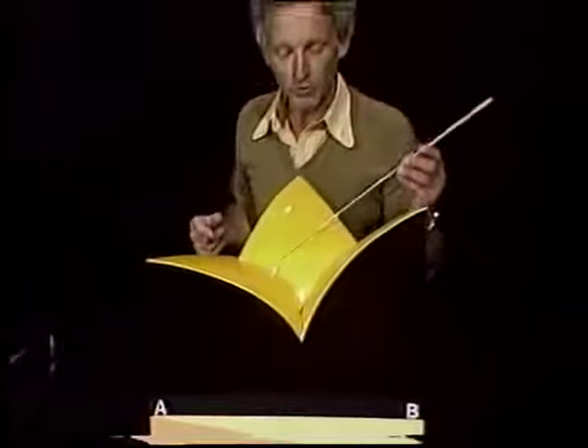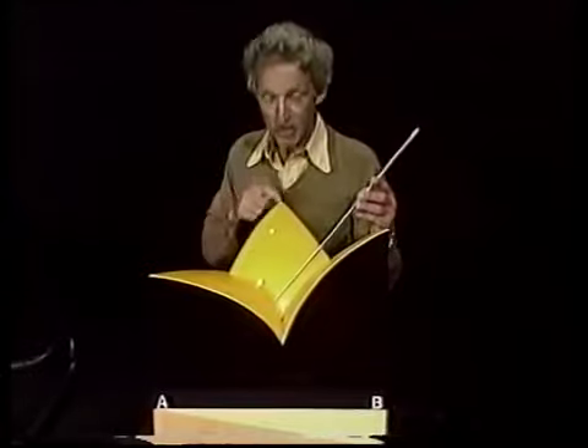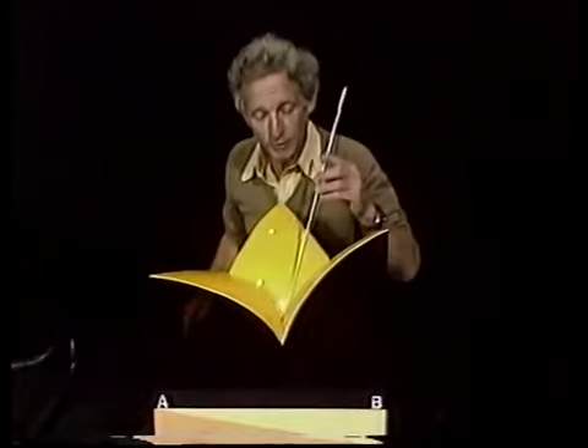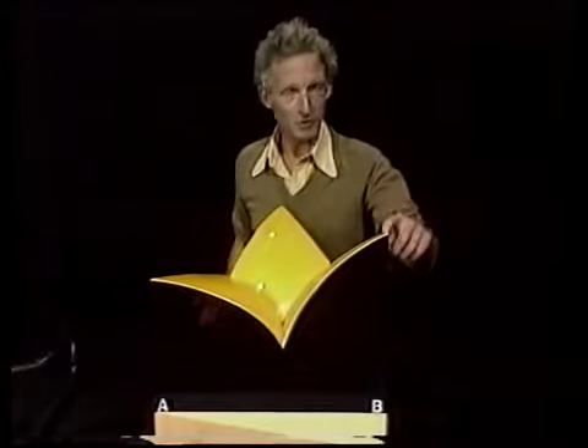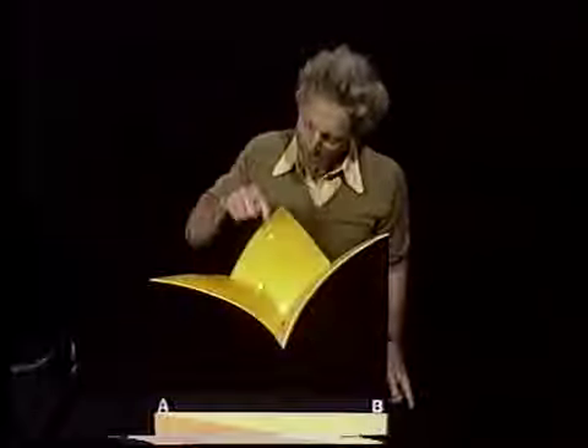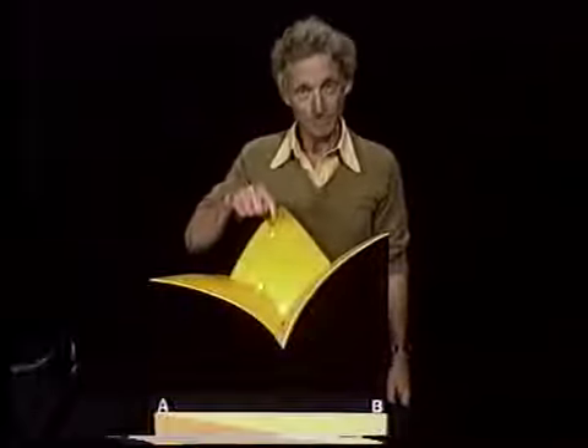Anyway, our melt goes on down the cotectic, crystallizing C and A as it goes, until it reaches the ternary eutectic. And there, something else has got to happen. Crystals of B have got to come out. And so the melt's going to stay there in the ternary eutectic at the composition and temperature of the eutectic, crystallizing A, B, and C in fixed proportions until all the melt's gone. But of course, the final solid product has to have the composition of the melt you started with.